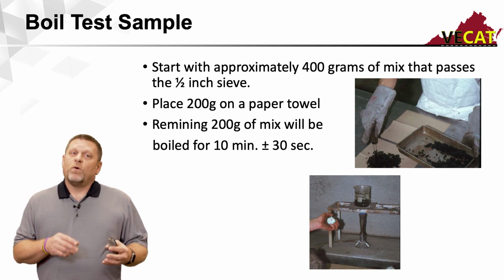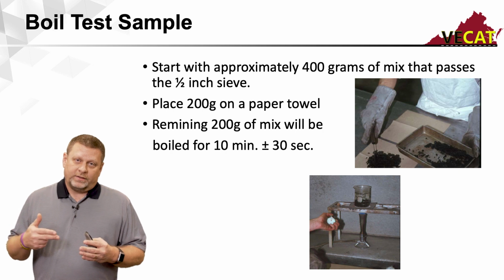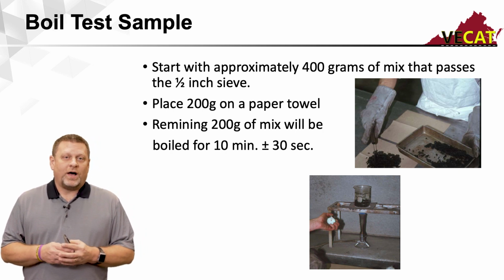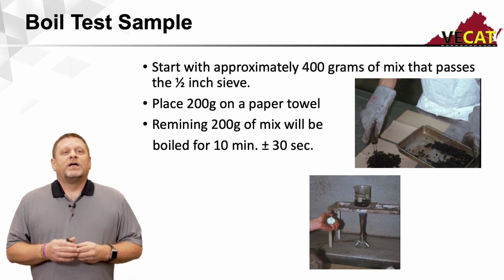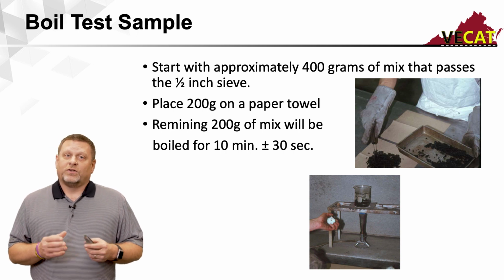Before I can put my mix in this boiling water, the water must already be boiling. So we don't want to wait for the water to begin boiling. You know the old saying, how long does it take for water to start boiling if you're watching it. But the point is, it goes in this boiling water for 10 minutes plus or minus 30 seconds.